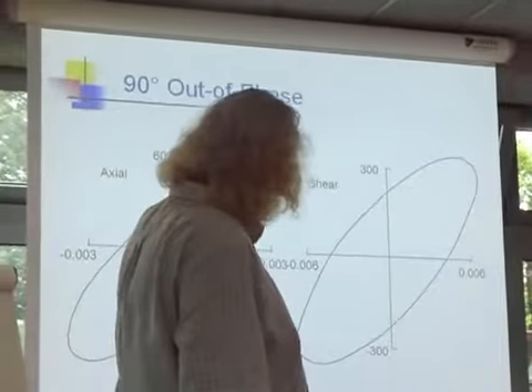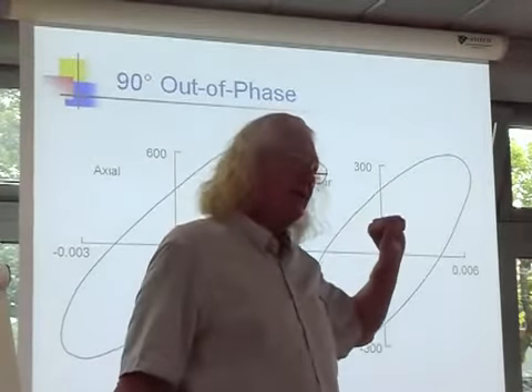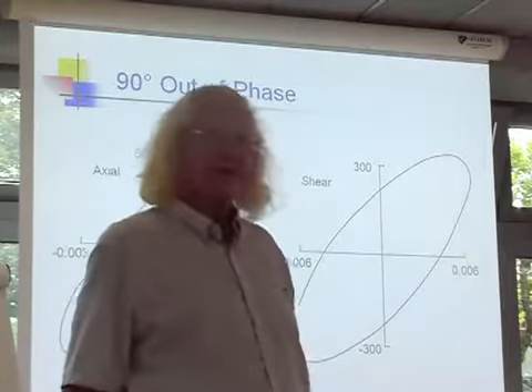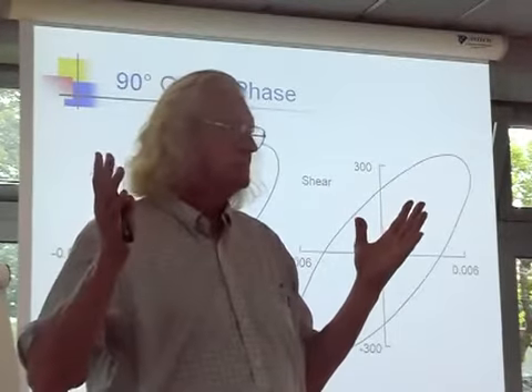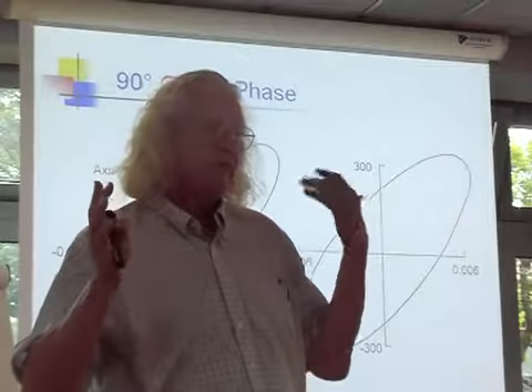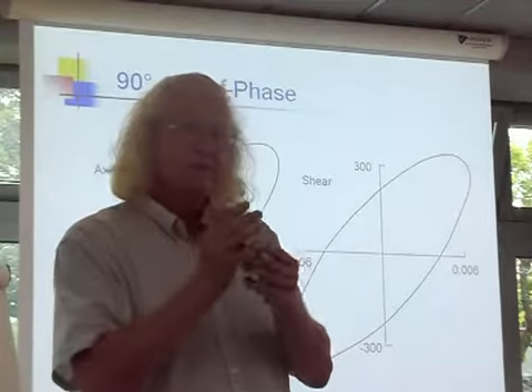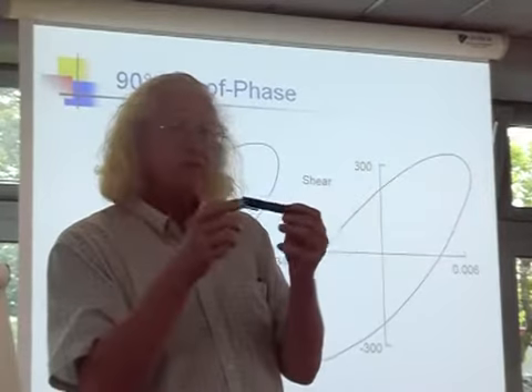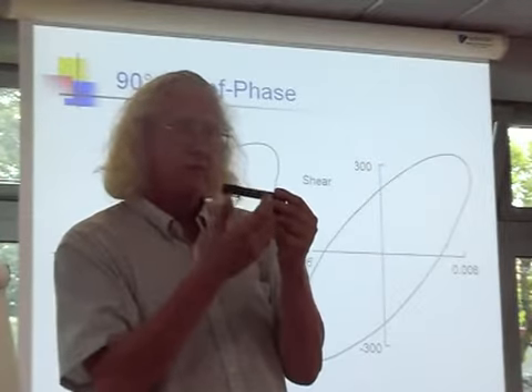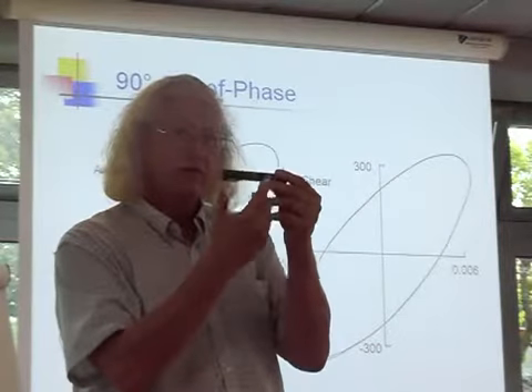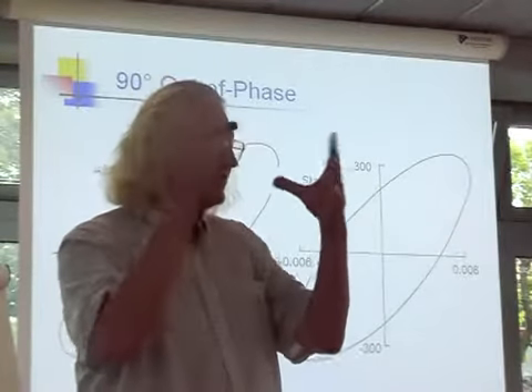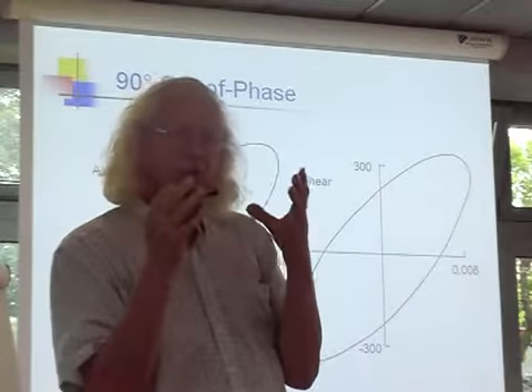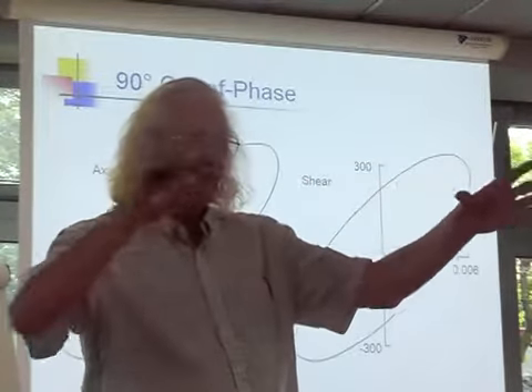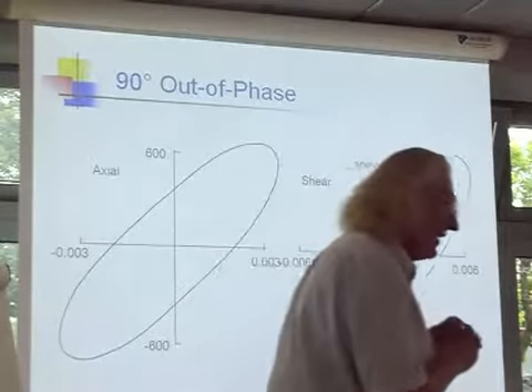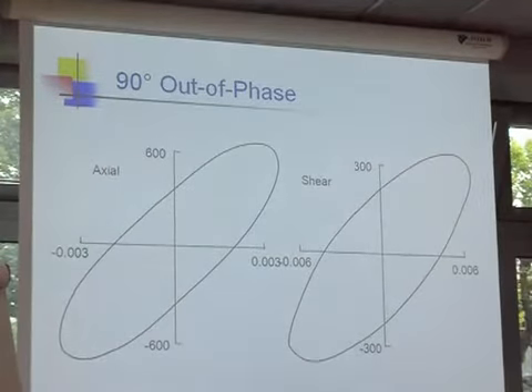So I expect if I could double the stresses, that I might change the fatigue life by a factor of 30. Does that make sense? Right? Because remember Morrow's ideas, right? I can strain something, but the material's resistance builds up a lot of stress, and both the stress and the strain must contribute. So if I do something to the material that can double the stresses, that must be more damaging. And we just went through a quick exercise to say that difference should be about 30. Okay? Well, let's see.